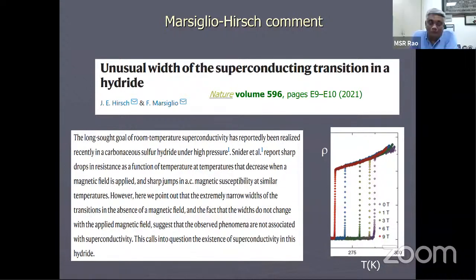So that is also one of my problems, Professor Peter. I see lots of papers on all these new exotic systems where there are all these sharp drops in the rho versus T curves, but then when you come to the magnetic data, the superconducting volume fraction is very, very small. So if it's just 5%, I don't know what's happening to the rest of the 95% of the bulk.